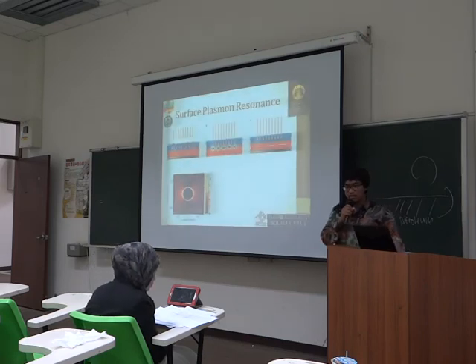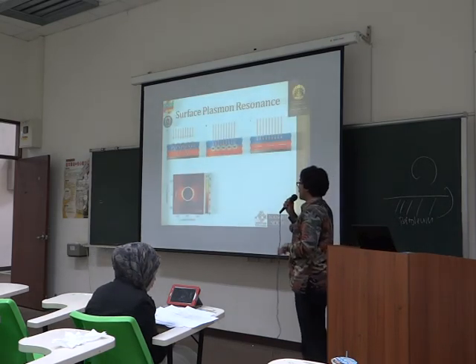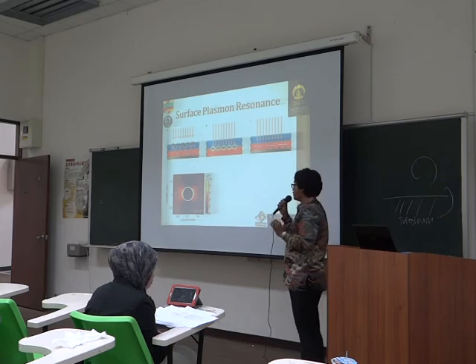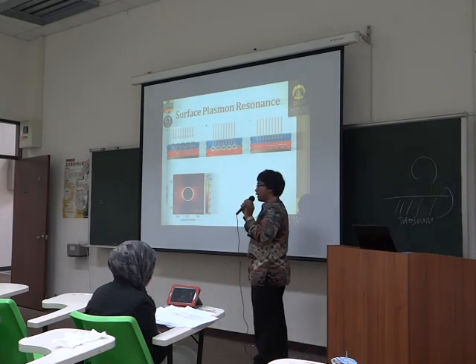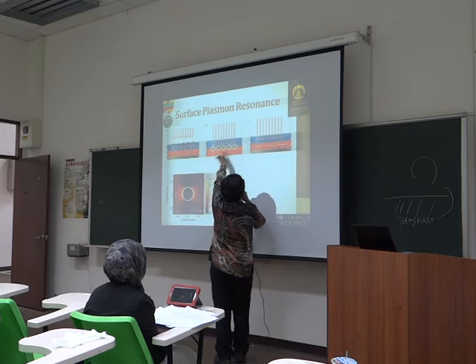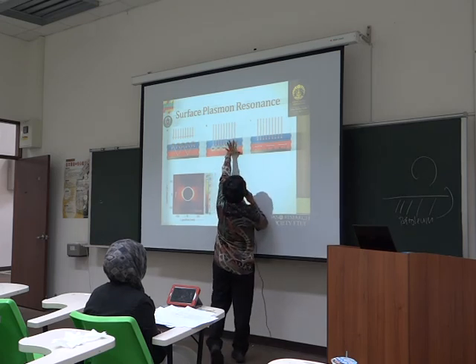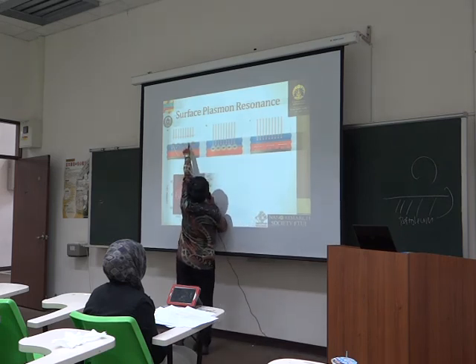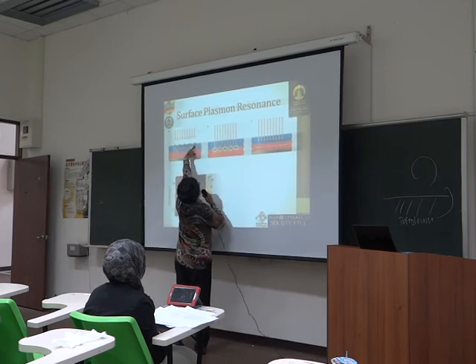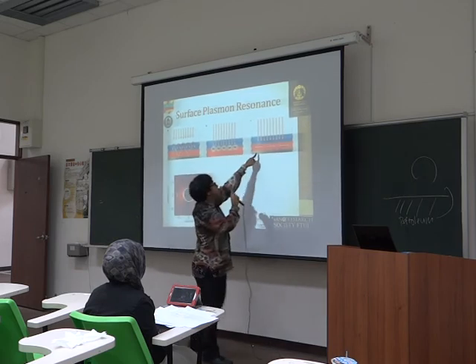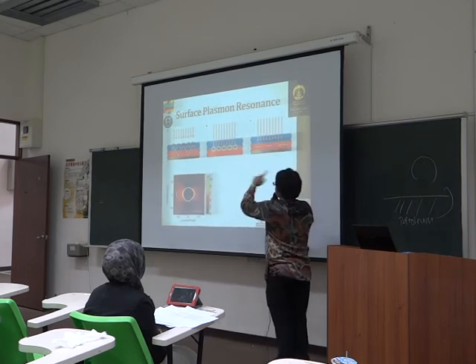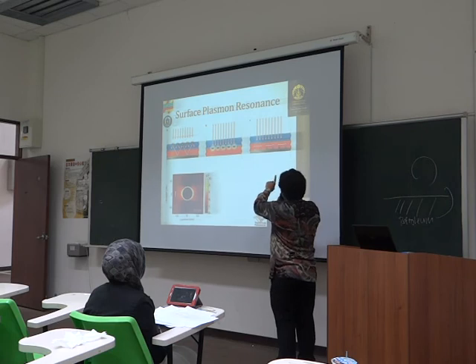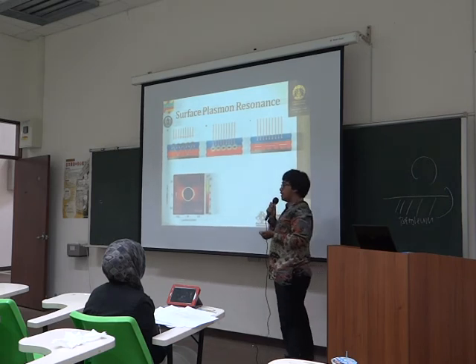This is actually the introduction of surface plasmon resonance. It's like a nanoparticle, like a gold nanoparticle, that can propagate the energy. So if you put it here, the energy received by the heat will propagate here, so it will not re-emit back. The energy comes here and will be trapped here, because if the energy wants to come back, it will collide here and come back again. If the energy comes, it will propagate, so it will not come back. So it's a strategy for us to use surface plasmon resonance to increase the efficiency.